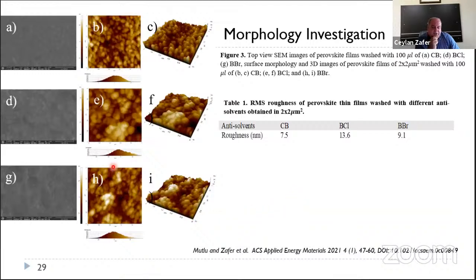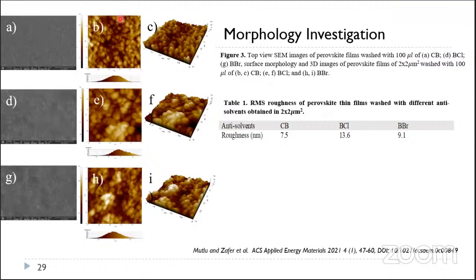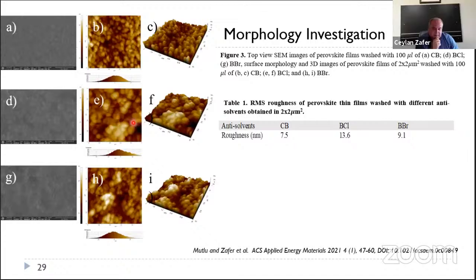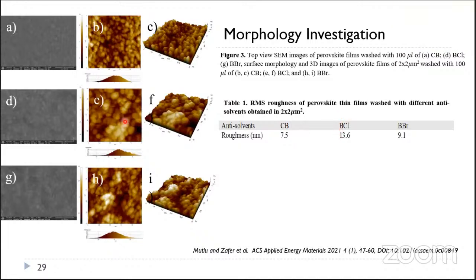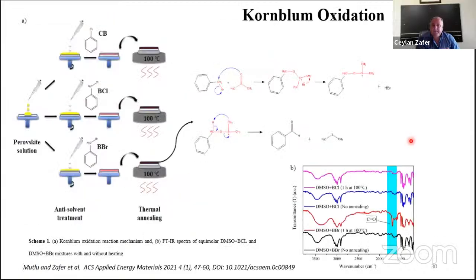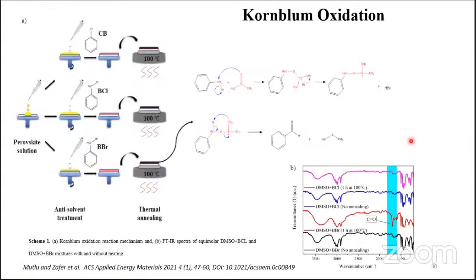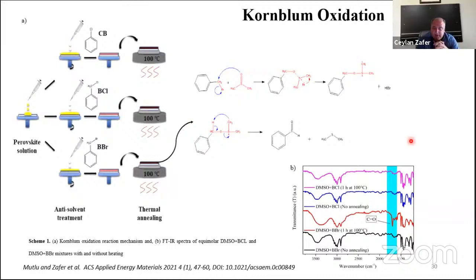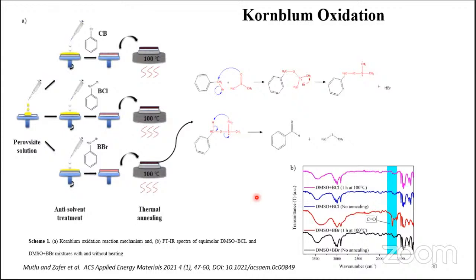Here you see the morphology changes with this treatment of different solvents. Here the particle becomes a little bit larger with the chlorobenzene, with the benzyl bromide. It becomes smoother again, with the RMS roughness as seen here. With this benzyl bromide or benzyl halogen treatment, the reaction goes through the Kornblum oxidation reaction, and the key point of this reaction is the removal of the very strong coordinating solvents that we use for the preparation of perovskite solar cells.